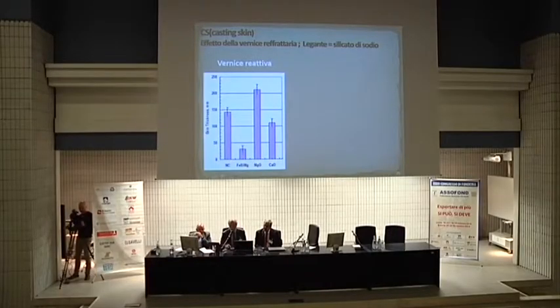And here is an example of reactive coatings. Like this is no coating, and this is when you add ferrosilicon magnesium. So actually you are adding a little bit of magnesium on the surface. So this ferrosilicon magnesium is mixed in the coating, and now you have a little bit of magnesium going back into your melt. Magnesium oxide doesn't have any effect. Calcium oxide has some effect, but ferrosilicon magnesium has a much better effect.